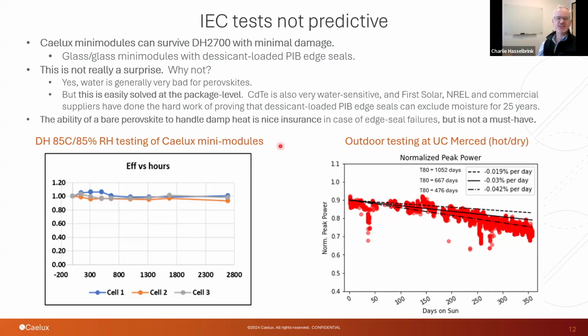It certainly is nice insurance if you do have a PIB edge seal failure. Those certainly do occur. Delaminations, or hey, it wasn't quite laminated long enough or something like that, quality issues. But it's not really a must-have. So my point here is that, even though in damp heat we had basically no degradation after 2,700 hours, we certainly degraded in the field. And this is in a dry environment. So I'm actually kind of using the field data point to say, hey, that doesn't correlate with the damp heat testing in that case.